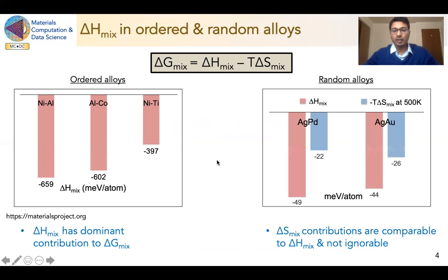But when we talk about random alloys, the enthalpy of mixing values are shallow. Shallow meaning they are close to zero, and thus entropy contributions become important. So, for example, in these two random alloys, silver palladium and silver gold, both are single phase solid solution alloys. And when we see their enthalpy numbers, they are of the order of 50 meV. And in these alloys, the entropy numbers at 500 Kelvin are around 25 meV, almost half of the enthalpy numbers, which makes both these quantities comparable. And thus, for this reason, entropy contributions cannot be ignored in random alloys.